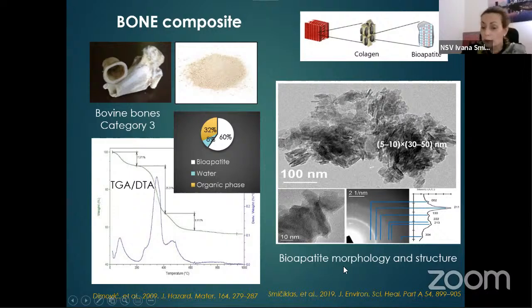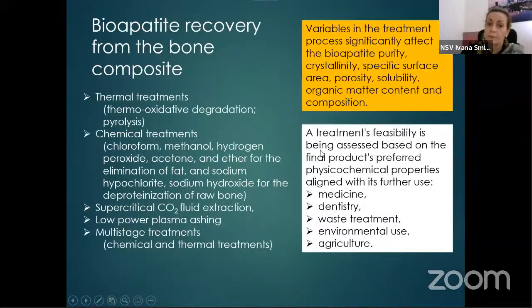If we look at the morphology and the crystal structure of the bioapatite inside the bones, we can see that the crystals are needle-like. They are of nano size, with 5 to 10 nanometers in one direction and 30 to 50 nanometers in the other direction. But although very tiny, these particles are crystalline and they show the characteristic crystal structure of hydroxyapatite.